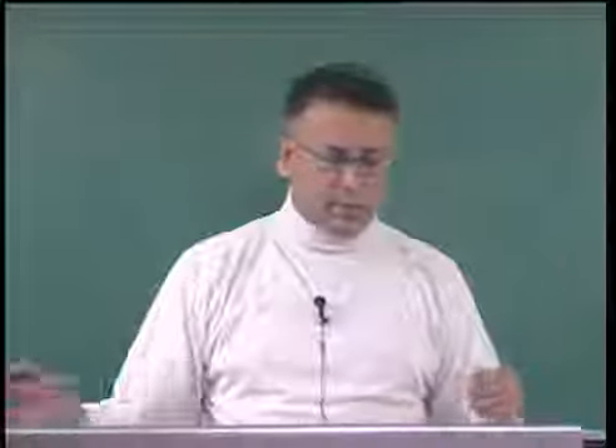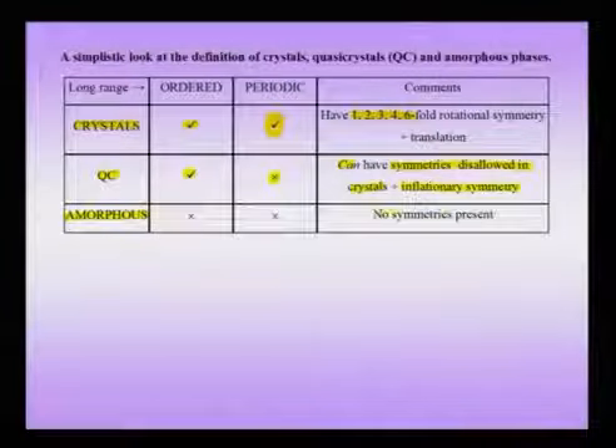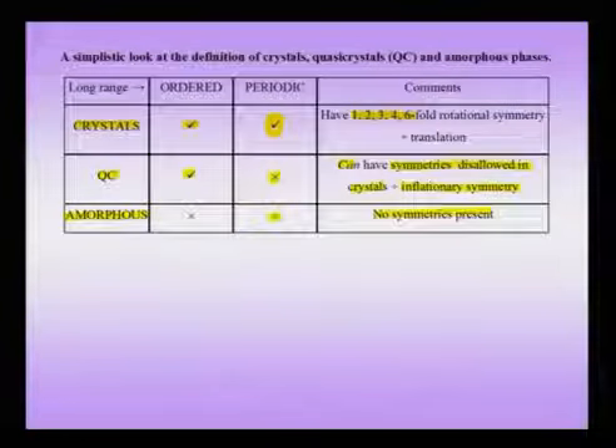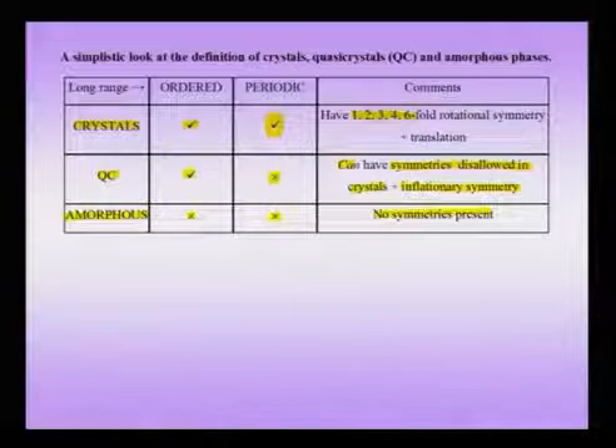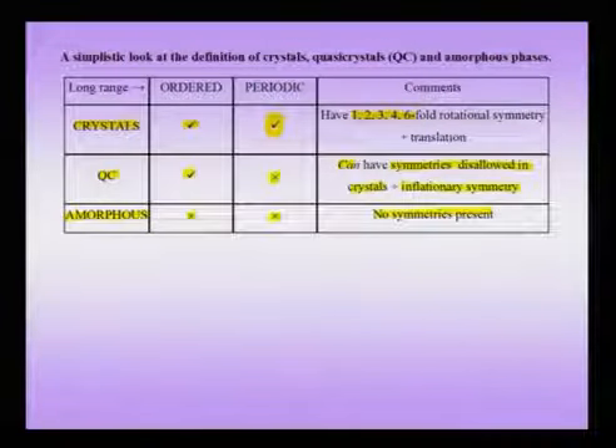The other end of the spectrum, as we saw, was the amorphous phases, wherein there are no symmetries present. That means it is neither periodic nor ordered. That implies that on one end of the spectrum I have crystals which are ordered and periodic, and on the other end I have amorphous phases, and often these amorphous structures are also called glasses. Though there is a subtle technical point which can be used to differentiate an amorphous structure from a glassy structure, for now we will not consider it. From an atomic structure perspective, we will treat them equivalently, and therefore an amorphous or glassy structure is neither ordered nor periodic.